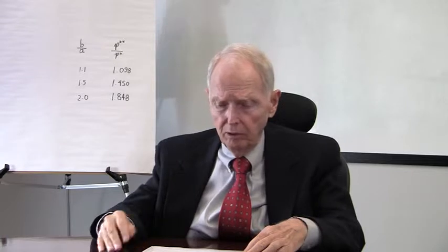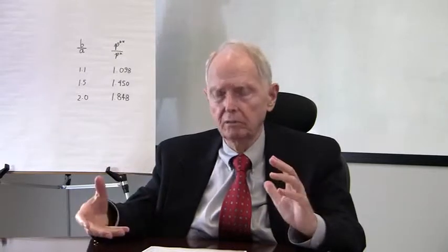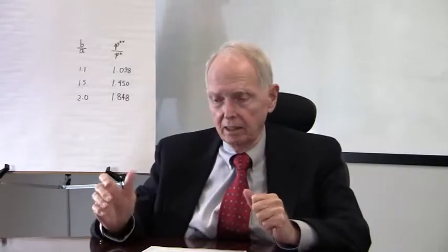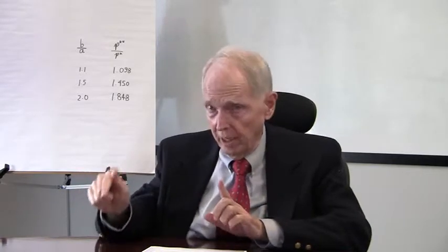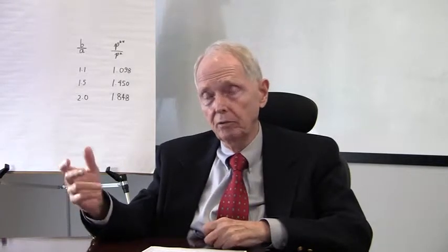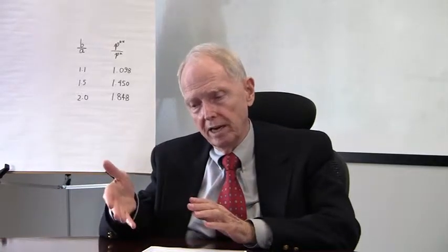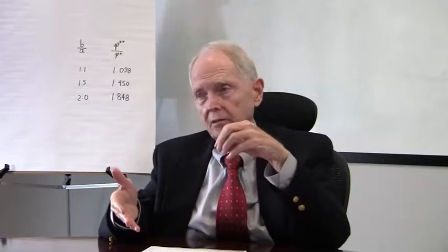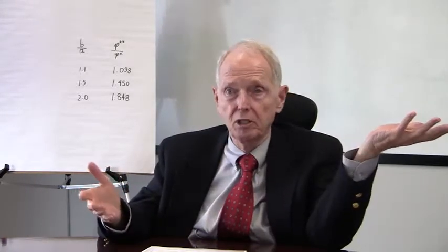Something worth noticing is that if you compare the torque for the cone, that is, you just twist and twist and twist, to the one where you twist elastically until the slope at the edge becomes equal to the yield point in shear. If you do that, then you have a torque, in this latter case, for initiating yielding. With the cone, you have as far as you can go. This would be sort of like collapse.